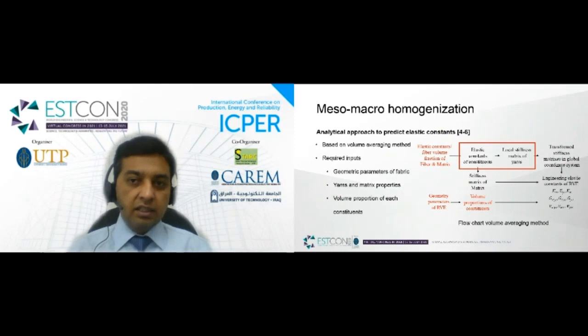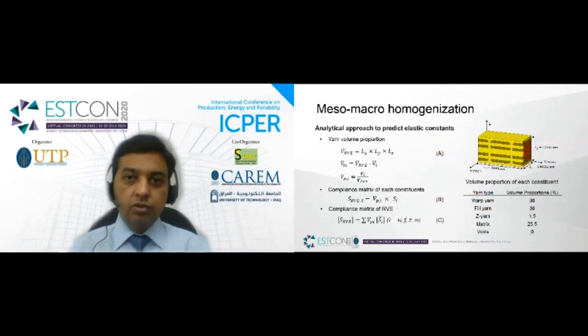In the first step, the elastic constants and respective stiffness matrices of impregnated yarns were determined in local coordinate systems. In the second step, the stiffness matrices are transformed with respect to their orientation in the RVE to get stiffness matrices in the global coordinate system, which is XYZ. And finally, the volume averaging method is applied to estimate elastic constants of 3D composites using transformed stiffness matrices and their volume proportions. The volume proportion of each constituent was determined using geometric parameters discussed earlier and RVE dimensions, using equation set A.